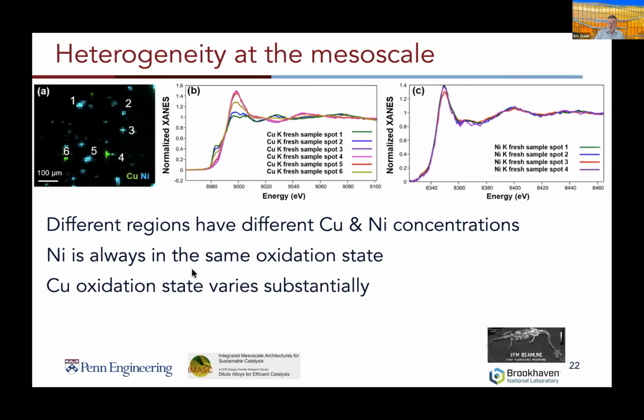So in this case, we went again back to the XFM beamline at Brookhaven. And interestingly, we found that if we looked at relatively high magnifications for that instrument, there were different regions of the sample that showed differences in the relative number of particles that had copper and nickel. And so it indicates that not only was there heterogeneity in the two types of particles, but some of them tended to cluster together to give, say, more copper in one region or more nickel in another.